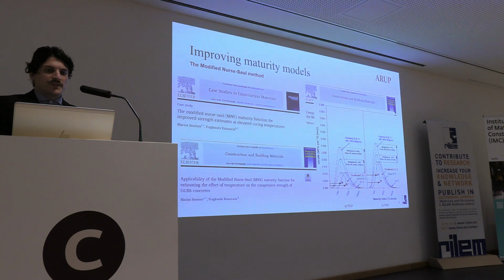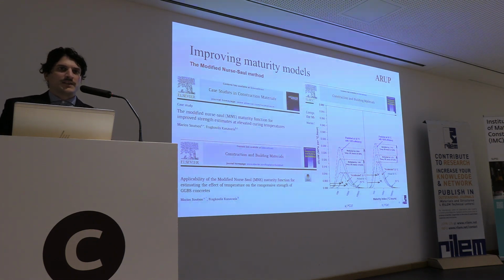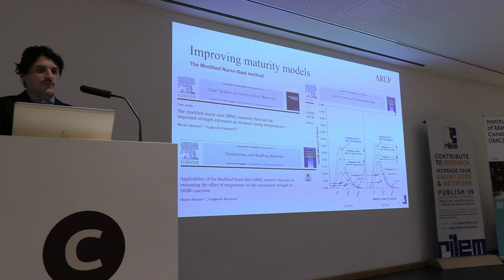But the concept is that normally people try to understand how the strength develops in terms of cumulative strength development at 1, 3, 7, 28 days, and so on. But with this method, we found that it's more important to understand the rate of strength gain and find a way to transform that rate from a reference temperature, let's say the standard curing temperature of 20 degrees Celsius, to another curing temperature, while taking into account the crossover effects. So with this method, we were able to dramatically improve the predictions of early age and long-term strength, and it can be extrapolated to other properties as well.